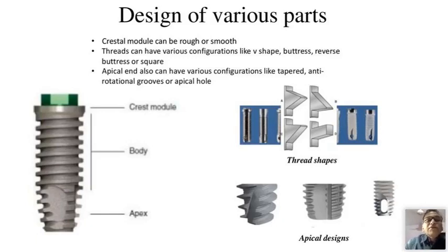The major thing for an implant is what type of threads should be there. So there could be various types of threads, for example A, B, C, D, which I have classified. There may be V-form threads. It can be buttress threads with a flat on top. It can be a reverse buttress, which is a flat at bottom, or a square shape. So there are more than 5,000 patents which are talking about different features of a dental implant when we started looking at the literature. And then even at the apical, there can be a helix, there can be a cut to collect the bone which gets drilled into this zone, or even there is a hole at this region so that it becomes a non removable feature, so that there is an anti-rotation element which can be provided.